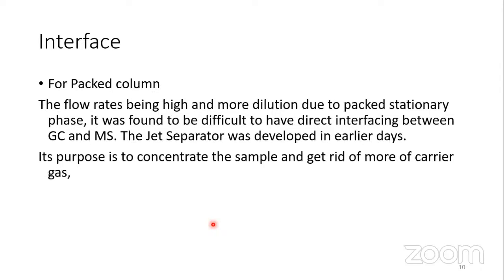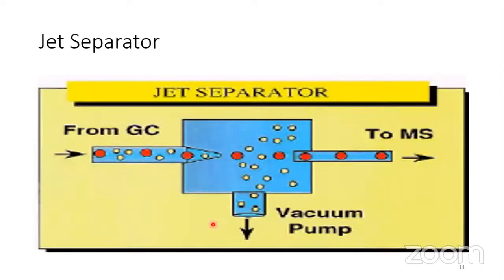Earlier, people were using packed columns. People still use packed columns, but to a very small extent compared to what we call capillary columns today. So packed columns were used for some applications where the flow rates are quite high. We generally use 20 ml to 80 ml per minute of carrier gas flow. And when you allow that flow to enter the mass analyzer, which works under high vacuum, the mass analyzer cannot accept that. And that is why you require to reduce the flow rate. And that is done by the interface, which is called the jet separator. By using a jet separator, one can reduce the amount of gas entering the mass analyzer and only sample enters. Most of the carrier gas goes out into the vacuum.